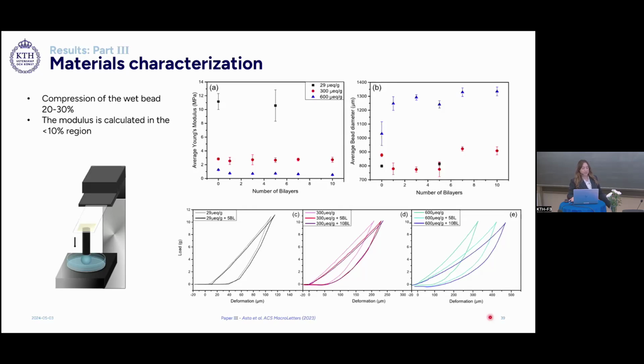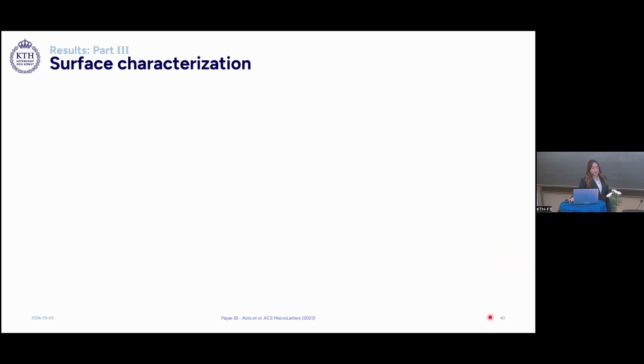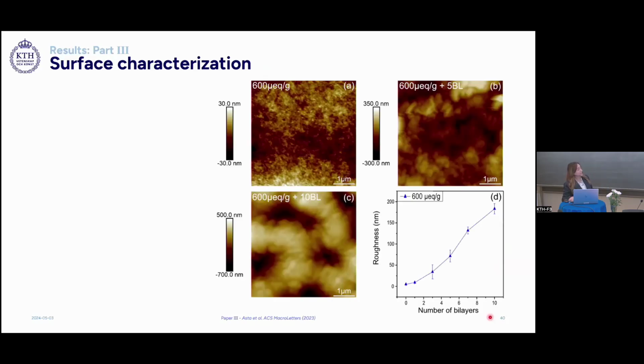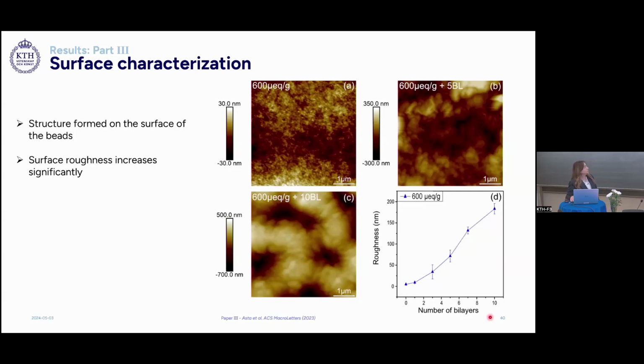And these adsorbed layers on the surface are expected to alter the structure of the surface of the beads. And this was analyzed by doing SEM, AFM of the surface of the dry beads before and after adsorption of 5 and 10 bilayers of PAH and HA. And we can see that there are structures formed on the surface, and the surface roughness increases significantly from about 5 nanometers up to 183 nanometers when adsorbing 10 bilayers.